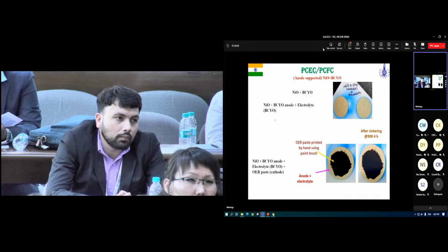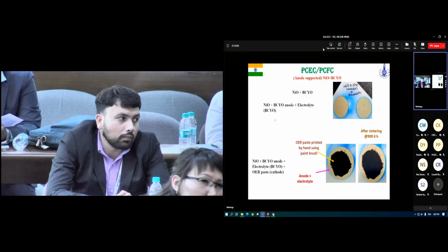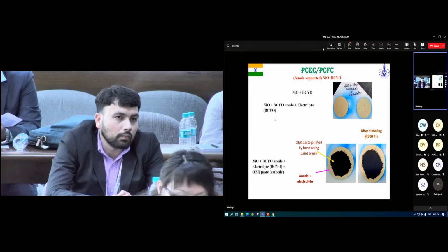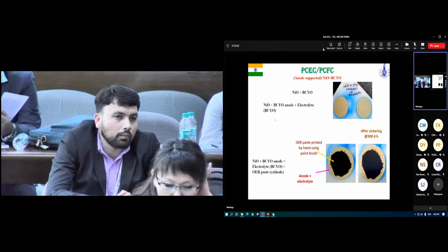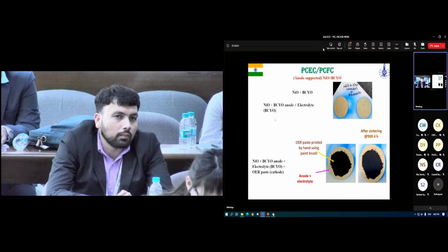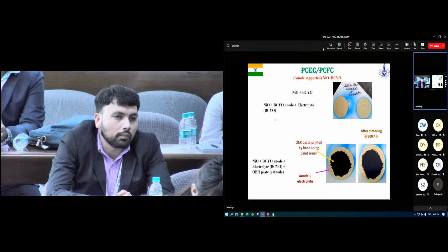There are two types of cells: anode supported, where we use the electrolyte on the anode. The anode is made up of anode plus electrolyte, and the electrolyte is a solid dense material, barium cerium yttrium oxide. These are the images of anode plus electrolyte. One side is the anode, and then we have deposited the electrolyte. Then we used our material, OER paste of that praseodymium nickel oxide material, over here by screen printing or by hand printing. So this is the whole cell, which we can now use for testing.